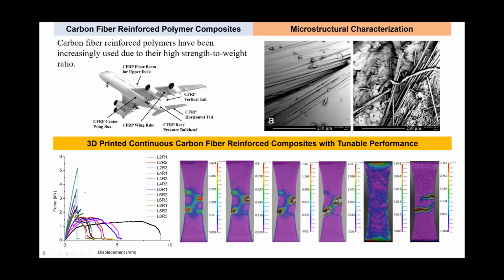So you can see we fabricated quite a few composites, and they exhibit very different mechanical behavior. From this plot, you can see some of them are pretty brittle, some of them are pretty ductile. So by varying the amount of continuous fiber, we can tune the mechanical behavior.